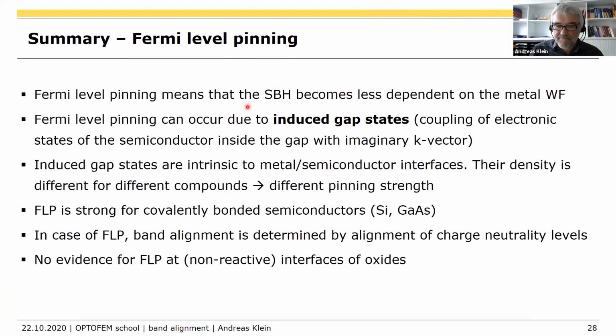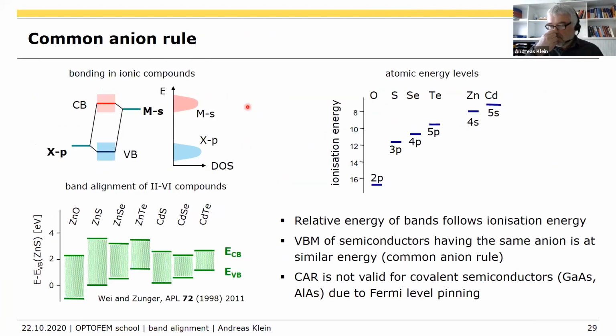Good. Then we continue. No more questions. So if it's not the vacuum level, and if it's not the charge neutrality levels, what is important for the alignment of the energy bands of oxides? There is something which is called the common anion rule. The common anion rule was proposed, I don't remember, in the 60s or in the early 70s. And it states that if you take 2 semiconductors which have the same anion, the valence band discontinuity between the 2 should be small.